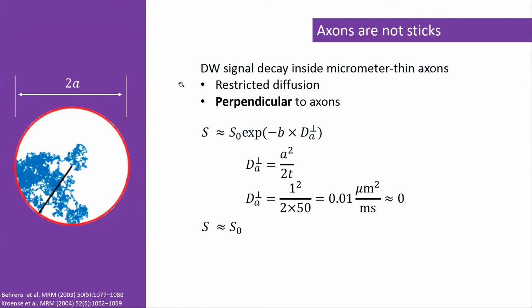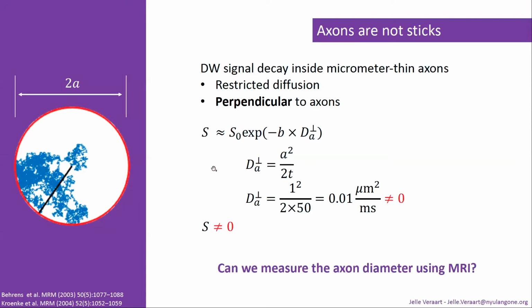And then we go back to this previous slide. In this previous slide, I showed that the diffusion weighted signal perpendicular to the axon is basically equal to its non-diffusion weighted signal. So basically the apparent diffusion coefficient is assumed to be 0. But that's not entirely correct. Almost 0 is not 0. So if there is actually contrast, we might be able to measure it.